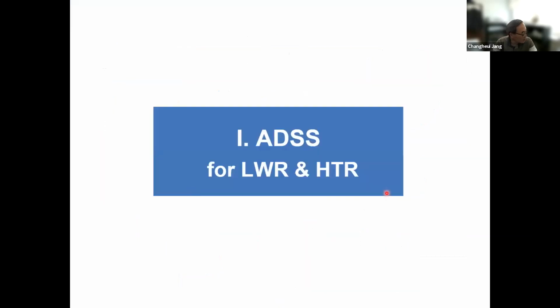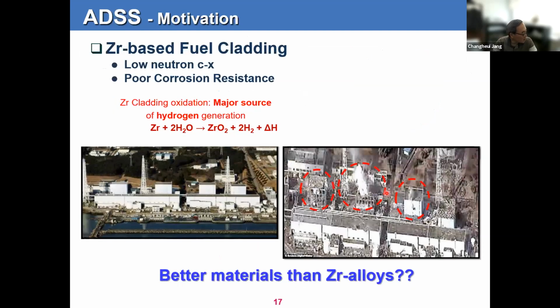The first one is ADSS for light water reactor and high temperature reactor applications. This is one of the very damaging pictures for the nuclear industry, which happened in 2011 at the Fukushima site in Japan. There are many reasons why this accident happened, but the consequences became much more significant because of the hydrogen explosion at the top part of the reactor building. Because of that hydrogen explosion, much of the radioactive material was released to the environment, and we had a significant evacuation in the nearby areas.